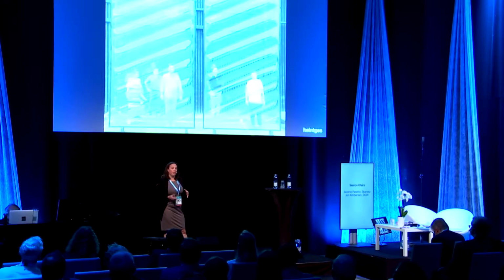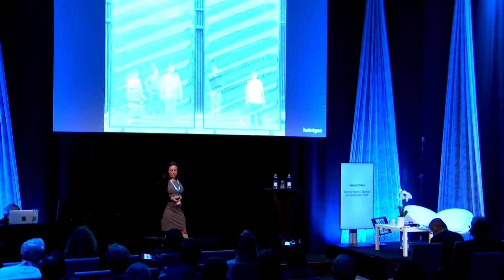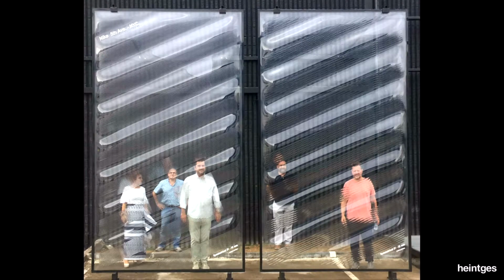From these samples, the final geometry of the glass was determined. Some of this came from the design team's refinements, and some of it came from the fabrication requirements and limitations. So there were adjustments in the width of the flat perimeter band, where the edge seal would lie, as well as the height of the slumped waves. And these revisions were then taken back into the analysis and checked again to make sure that the structural acceptability of the glass form was okay.